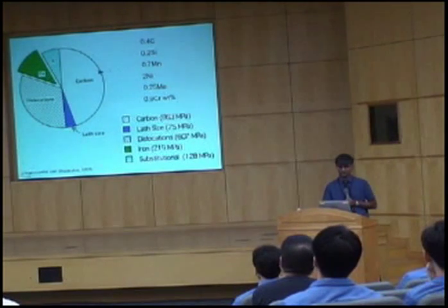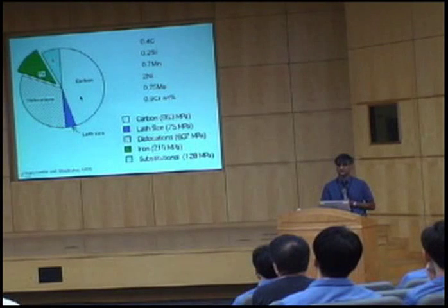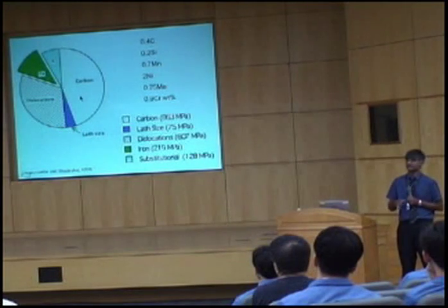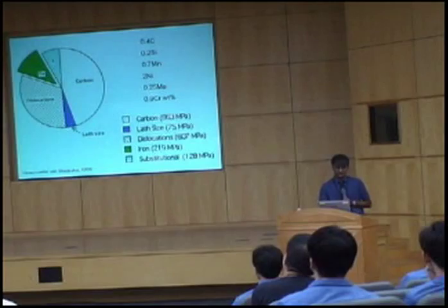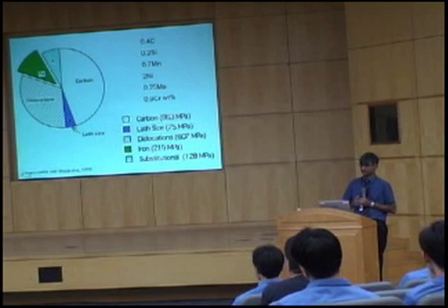This component will be more or less absent in the case of bainite, because the carbon is either precipitated as cementite or it is partitioned into the austenite. So we cannot rely on this to produce a great deal of strength in bainite. In ordinary steels, the thickness of the plates is of the order of a quarter of a micrometer. So the contribution to strength from that is significant, but it's not very large.